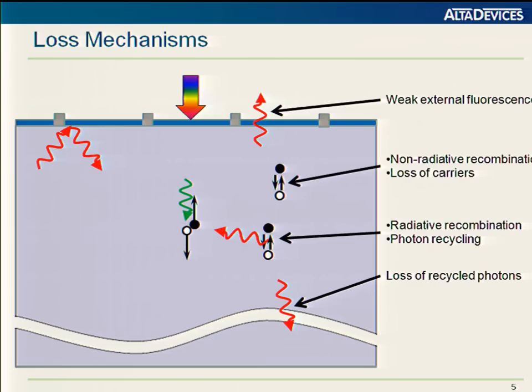And this is a very different kind of photon from the incident light. This is an old PL spectrum from one of our devices from a couple of years ago. The point I'm trying to make is that its width is something like plus or minus 20 nanometers, as opposed to the solar spectrum, which was very broad. So it's really defined by the band edge energy and wavelength. So I've drawn these in red to represent the effective red shifting of the energy.